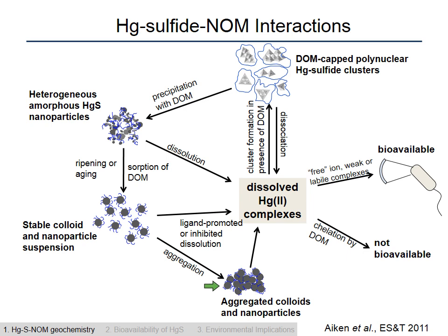These amorphous particles would ripen over time, as well as aggregate, and organic matter would be coating these particles during this whole process. And this process, going from the top to the bottom, I kind of see as an aging process for mercury sulfides, in which at every step the mercury has different potentials for redissolving back into the pore water. And so you have all of these processes occurring at the same time, in which the extent of each process is limited by the rate as opposed to reactions at equilibrium. And so some subset of this mercury will be able to dissolve before it's taken up by microorganisms that then can methylate the mercury.